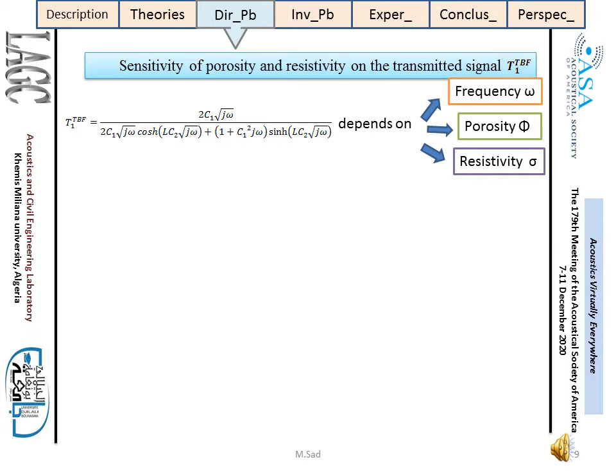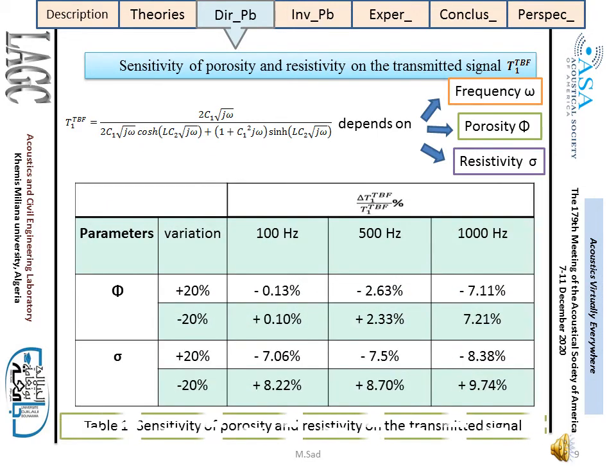Sensitivity study of porosity and resistivity on the transmission coefficient T1 is presented. Table 1 shows the relative variation of the transmission coefficient T1 corresponding to a variation of 20% of the porosity and the resistivity of the porous medium at different frequencies. According to table 1, the sensitivity of the porosity on the transmitted signal is negligible at very low frequency, and the sensitivity increases with frequency, while the sensitivity of the resistivity is important at very low frequency.